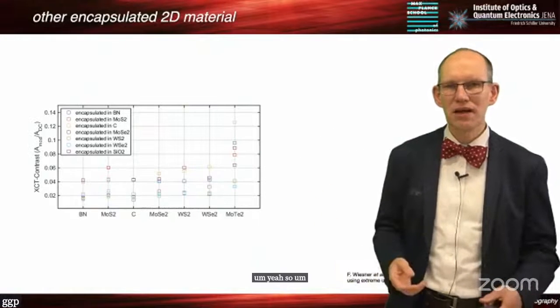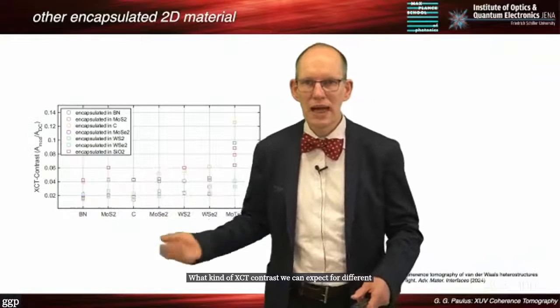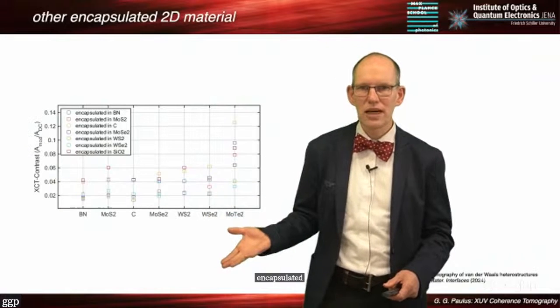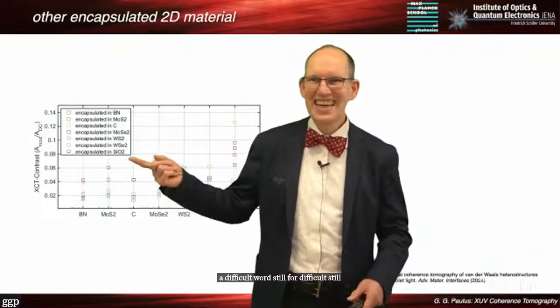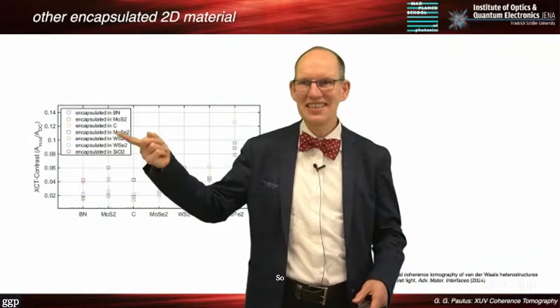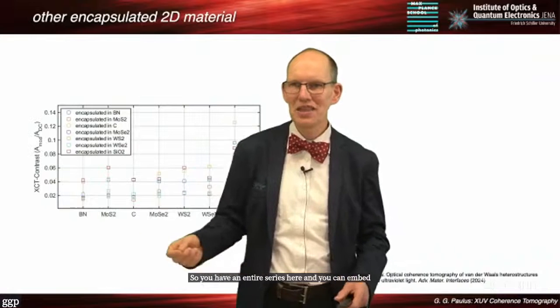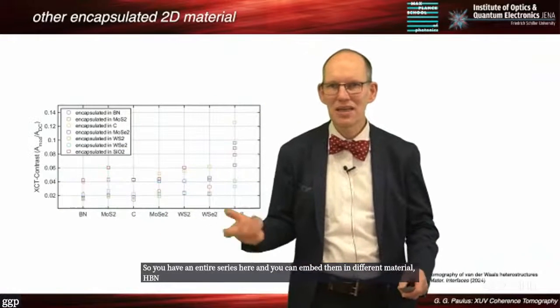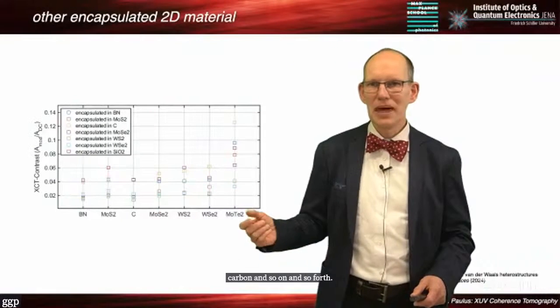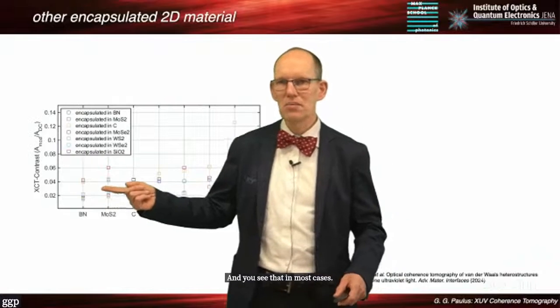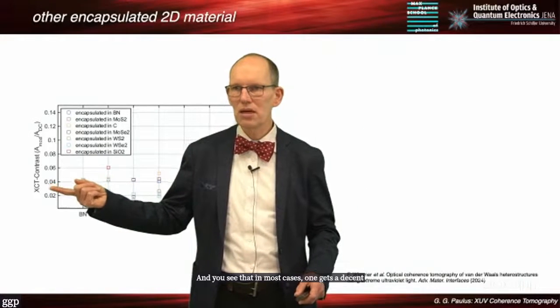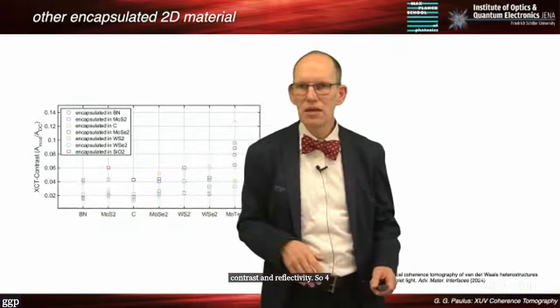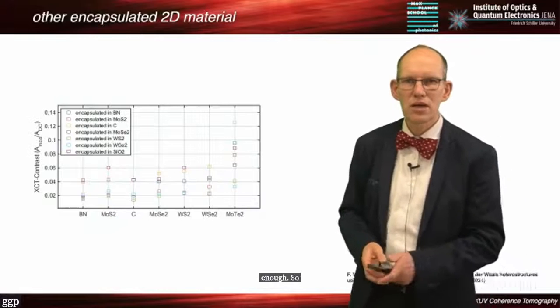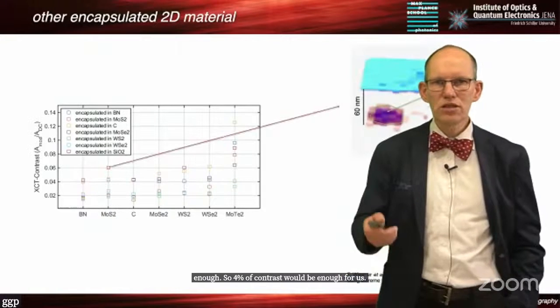Looking at the available data, what kind of XCT contrast we can expect for different encapsulated dichalcogenides. A difficult word still for me. So you have an entire series here, and you can embed them in different materials, HBN, carbon, and so on and so forth. And you see that in most cases, one gets a decent contrast and reflectivity. So 4% is typically enough. So 4% of contrast would be enough for us. So we tried it out.